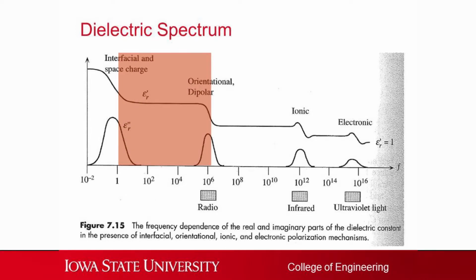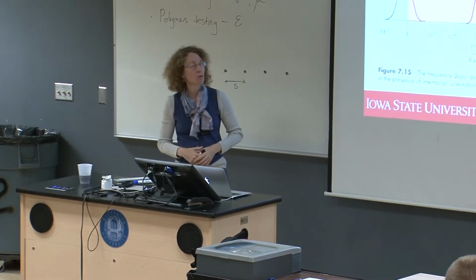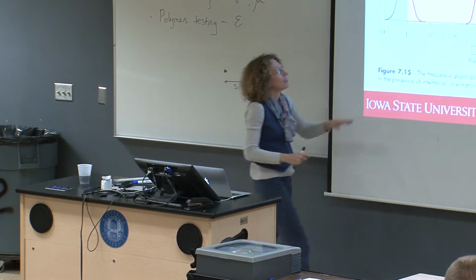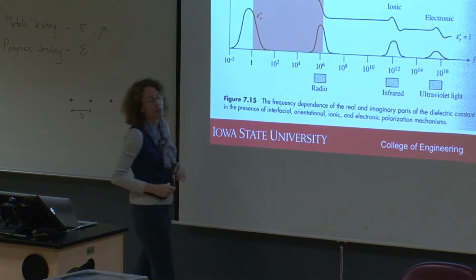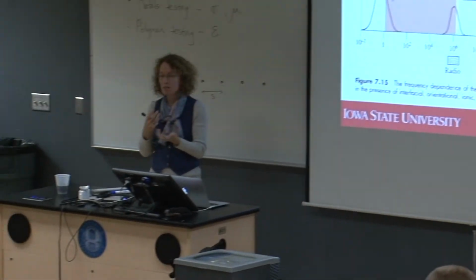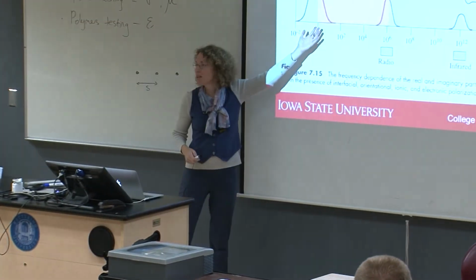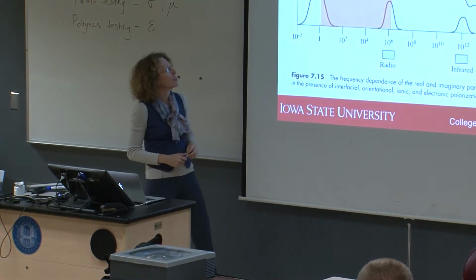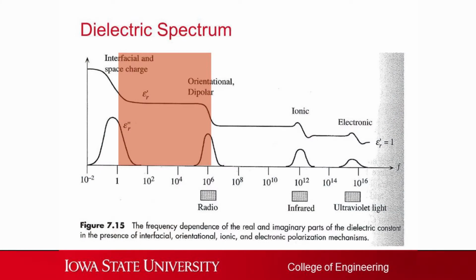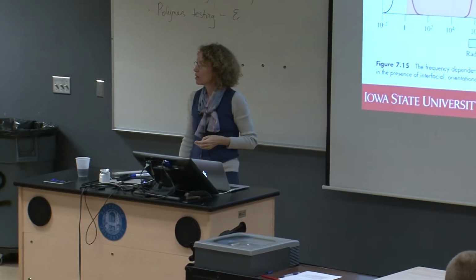So again, in this case, frequency information tells us more about the material. If we change frequency rather than doing it at a fixed frequency, we can determine more about the material. And this is the range that I typically work in for sensors that can be used in the field. It's a typical LCR meter type range of frequencies. And what you see is this is only a schematic, but this is roughly the right range for looking at those polymer polarization mechanisms, the dipolar mechanism.